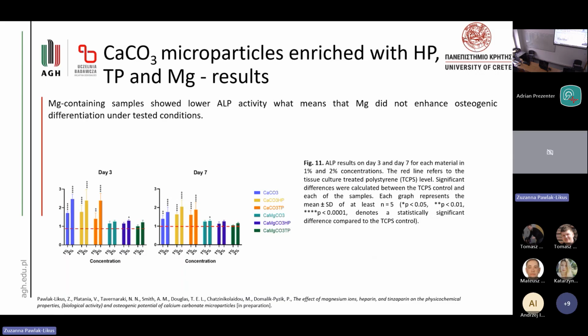And here are the results of ALP activity. To make it easier, what is ALP? It is the alkaline phosphatase assay that measures the activity of alkaline phosphatase, an enzyme that is expressed by osteoblasts during early stages of osteogenic differentiation. So ALP indicates early osteogenic differentiation and functional activity of osteoblast-like cells. What was quite surprising for us was that under those conditions, magnesium didn't support osteogenic differentiation. But as we can see, all the samples achieved better results than our control. So all of the samples supported osteogenesis, though the samples without magnesium supported it better.